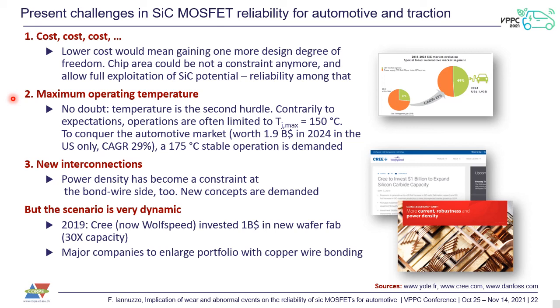And in my opinion, this is also limiting the possibility of increasing power density and efficiency thanks to silicon carbide. Because on the one hand, you can use a lot higher power density, but on the other, you have to limit the maximum junction temperature. So it's not clear to me what the benefit is of transitioning to silicon carbide, as far as the operating temperature is limited at 150 or 175.